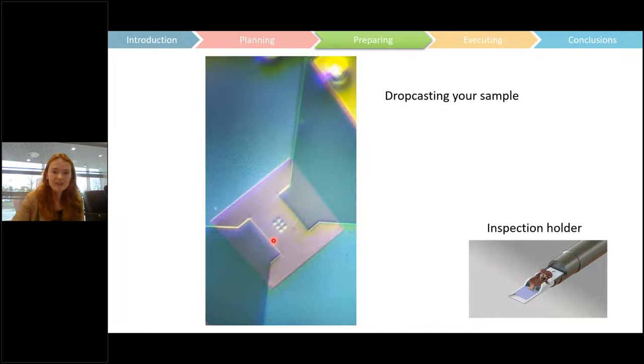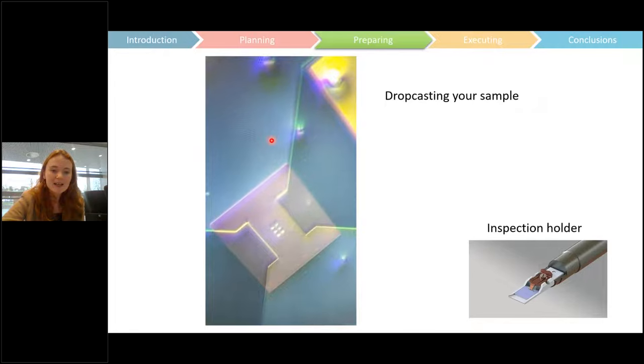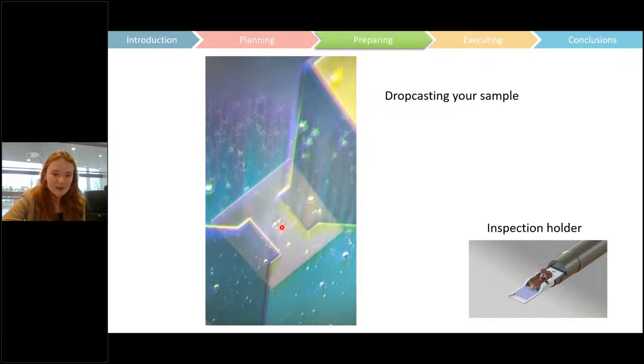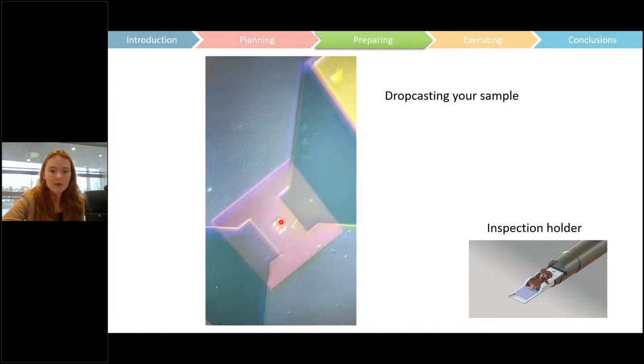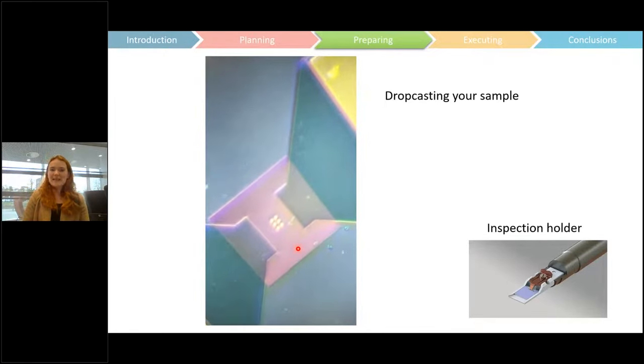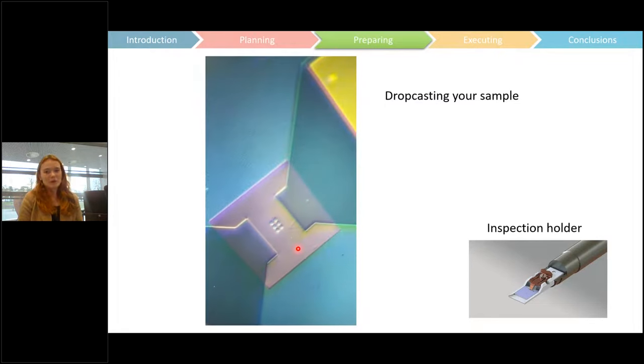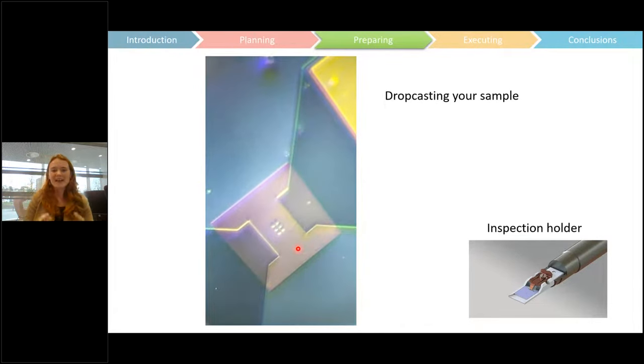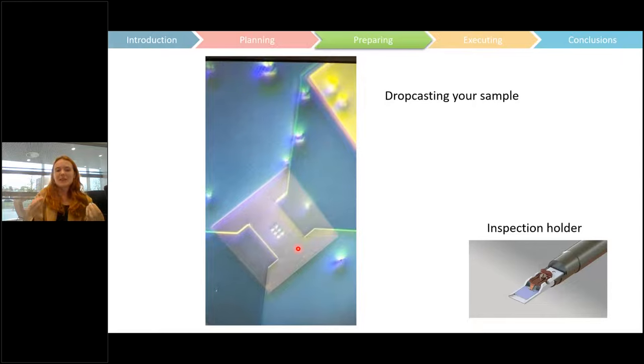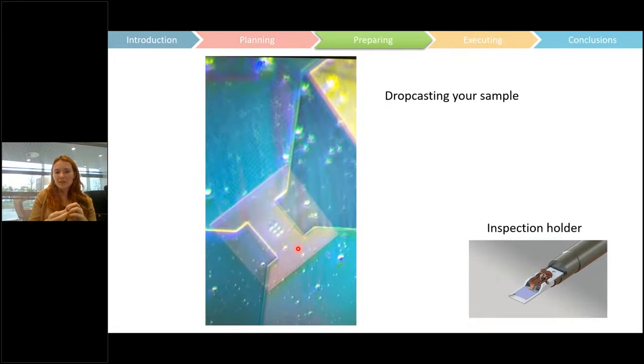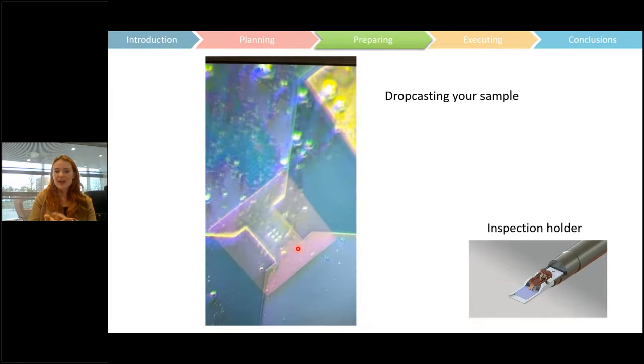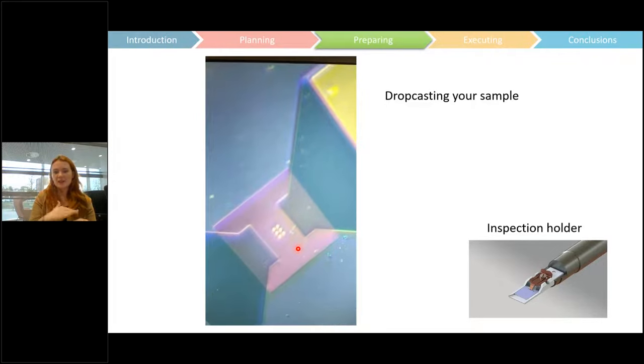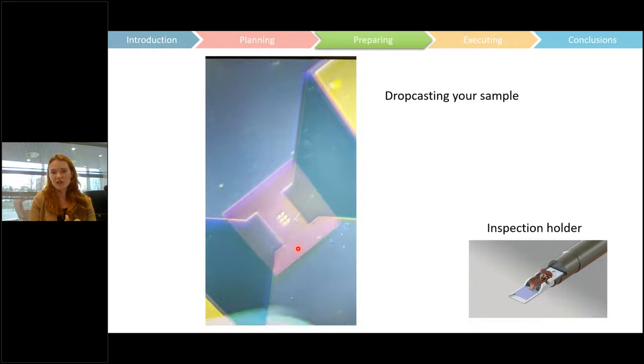Yeah, so here's the droplet that's landed. As it dries, you can really see every single little particle and where it has landed. If you are preparing samples, it is usually better not to do more than one or two drops, because after that the particles start to land always in the same places. So you just build up bigger and bigger clumps of particles as they stick together, as opposed to getting a finer and finer spread and more particles on your chips.